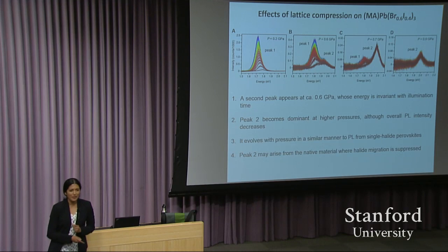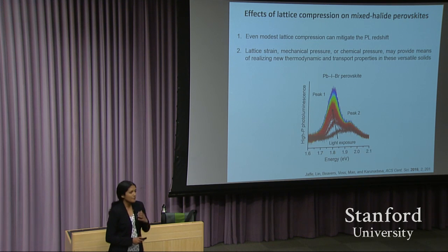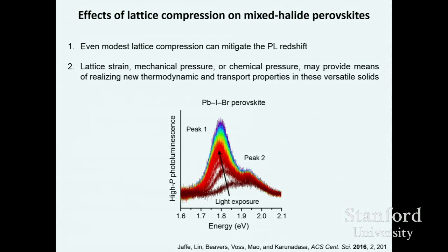So pressures above 1 GPa are probably not practical to apply in a photovoltaic device, but there are different ways that you can access pressure. Certainly you can squeeze the material, but there are also ways of exerting chemical pressure. This is done by adding very large cations into your lattice that don't quite comfortably fit with respect to their nearest neighbors, so it pushes its neighbors away. Theoretical studies have shown that the chemical pressure you exert can really mimic the properties of mechanical compression.